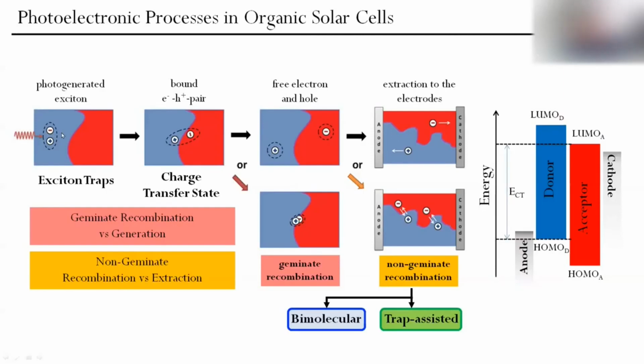If we have too small domains, then it will be very difficult to extract these charge carriers from the active layer. So there should be a balance between size of the domains of donor and acceptor. So once this exciton reaches interface, because of energy difference of LUMO of donor and LUMO of acceptor, and the same for HOMO, this energy difference can be used to split the exciton and create free charge carriers. It's so-called hole, positively charged, in the donor material and negatively charged electron in acceptor material.